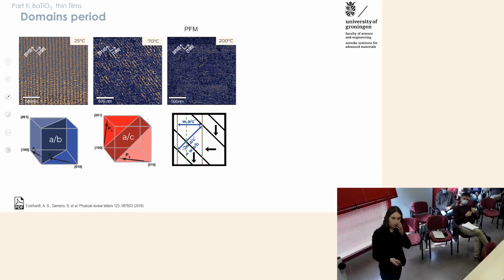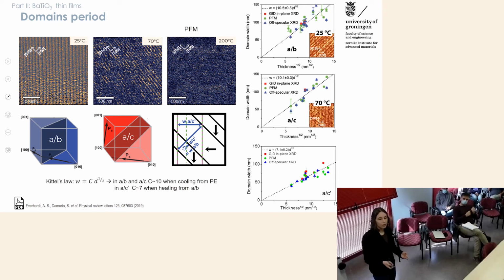So the first thing that we can do is also measure the periodicity of these domains as a function of the thickness of the films. And what we expect, as we saw in the introduction, is a periodicity that scales with the square root of the thickness of the film. And indeed, this is what we found in the AB phase and the AC phase, and we have this prefactor parameter of about 10. And this depends on the properties of the material. So in general, it's expected to be the same in all the phases of the same material.